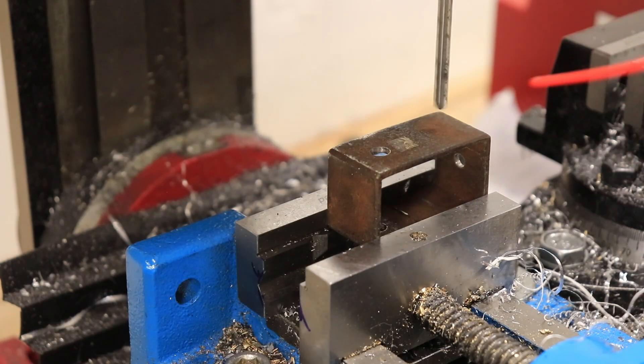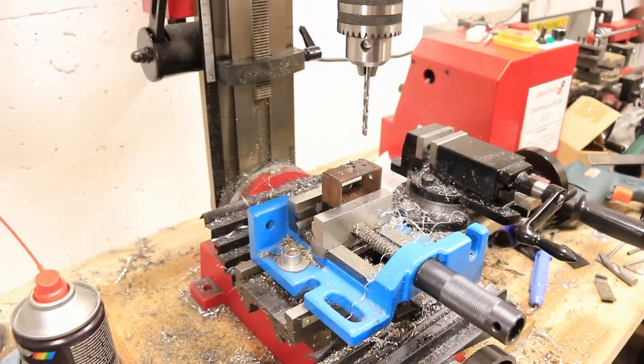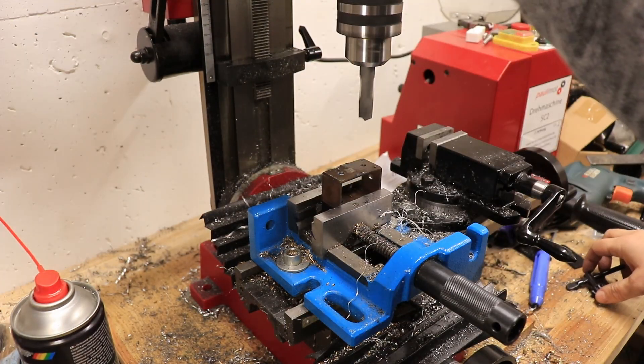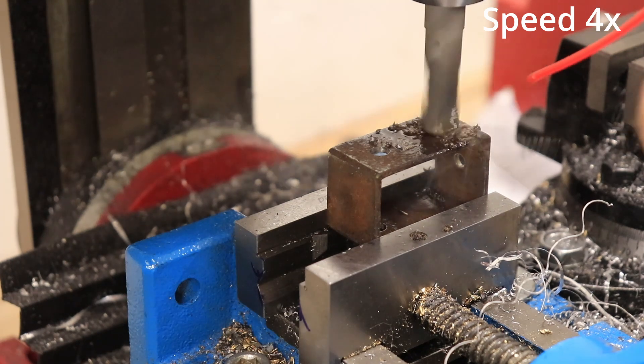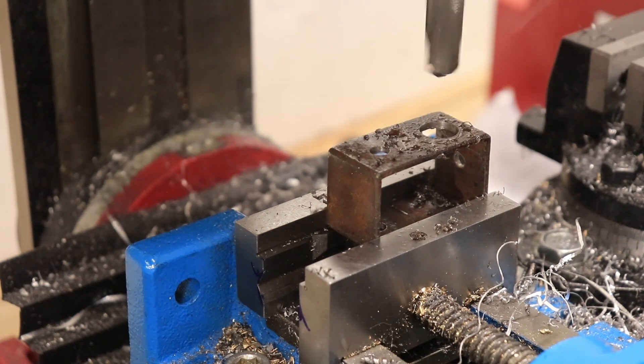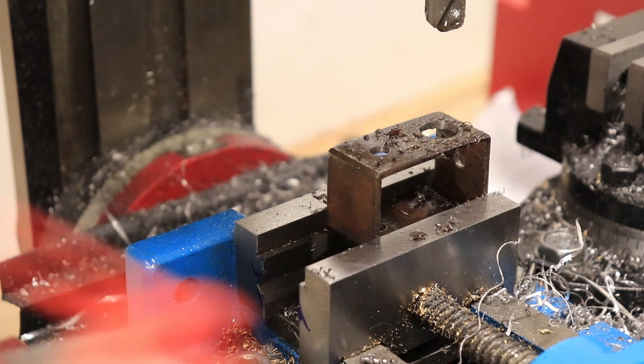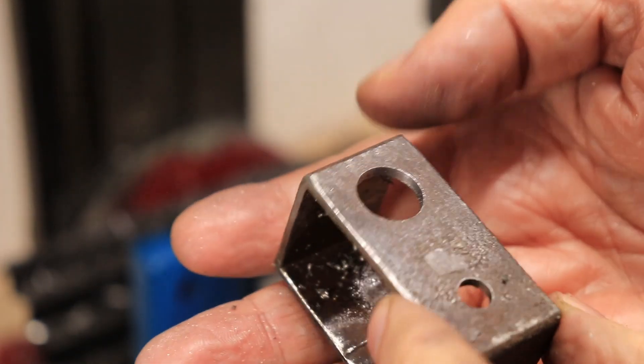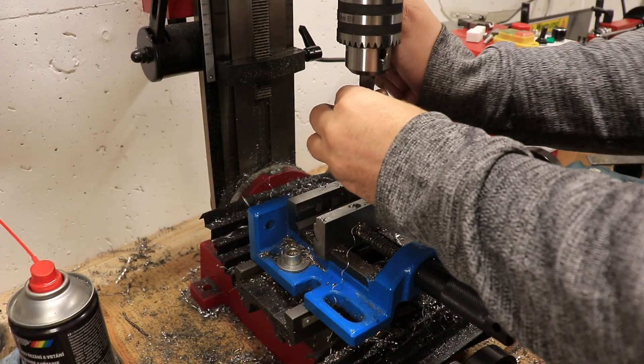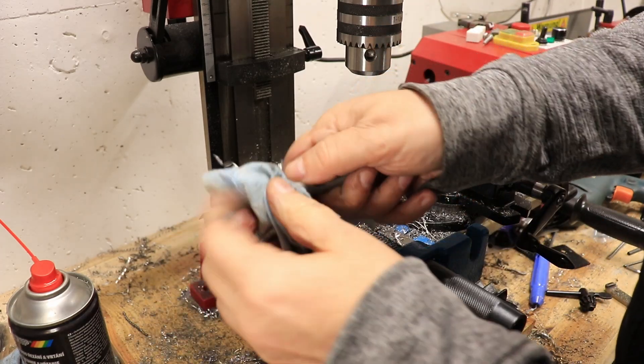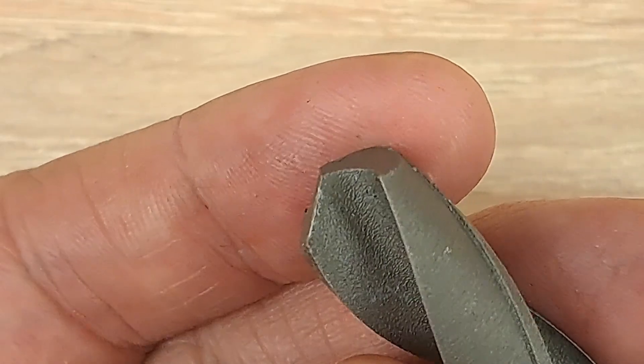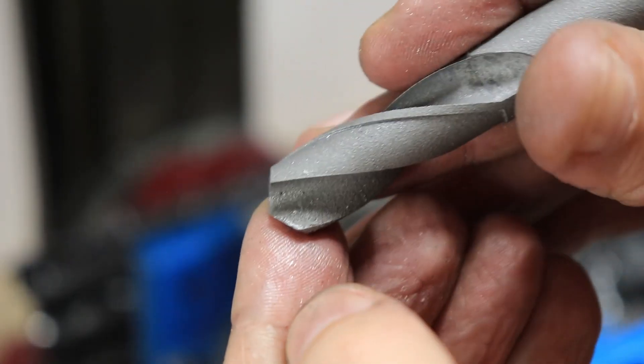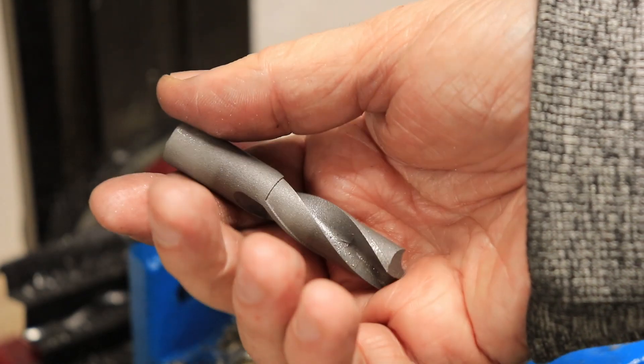And now regular steel, and creating again the 5 mm pilot hole. The smoke you see is the burning of the lubricant. The hole is perfect. And now let's see the twist drill. It is not too hot, so that's a good sign. Well, you cannot see maybe in the camera, but I can confirm definitely that this is very sharp, like before these two drillings. Both edges. 3D printed twist drill which can drill steel.